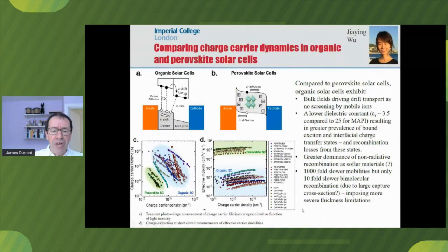We've heard a lot about perovskite solar cells in this conference, so I thought I'd just touch on some of the differences between the perovskites and the organic solar cells. When we compare the two, one of the obvious things you've heard about with the perovskites is they have mobile ions, and those mobile ions will tend to screen the bulk fields in the device, so the transport in the bulk of the device is probably diffusion driven. In the organic solar cells, we don't have mobile ions, and so when we have anode and cathode of different work functions, at short circuit you get bulk fields in the device which drive drift currents to the opposite sides. One of the biggest differences between the organic materials and perovskite is their difference in dielectric constant. Most organics have dielectric constants around 3.5, while MAPbI3 is around 25.